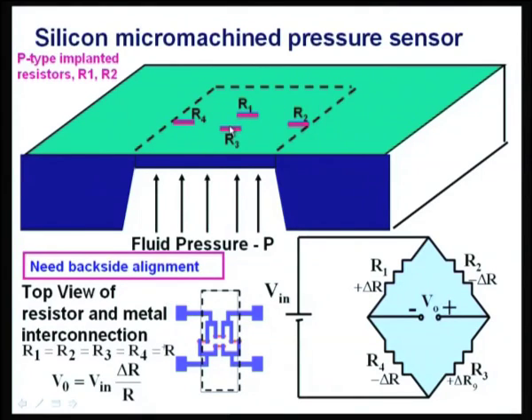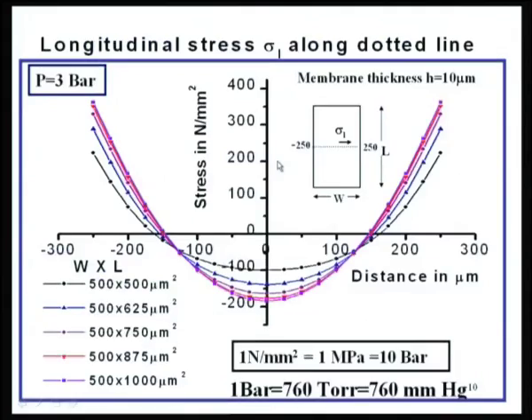If you plot the stress along this center line of the membrane, it will be tensile at the edge, positive meaning tensile. As you move from left to right along the center line, the stress is tensile here along that direction. You can see the square type of membrane, W is 500 micron, length is 500 micron. This is the lateral dimension of the membrane. So, at the edge, minus 250, the width is 500 microns, I take the center at 0.